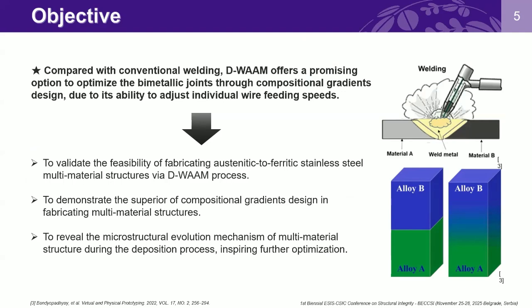Therefore, the objectives of this work can be summarized as follows. First, to validate the feasibility of fabricating austenitic to ferritic stainless steel multi-material structure via the dual wire process. Second, to demonstrate the superiority of compositional gradient design in fabricating multi-material structures. And the last is to reveal the microstructure evolution mechanism of the multi-material structure during the deposition process, inspiring further optimization.